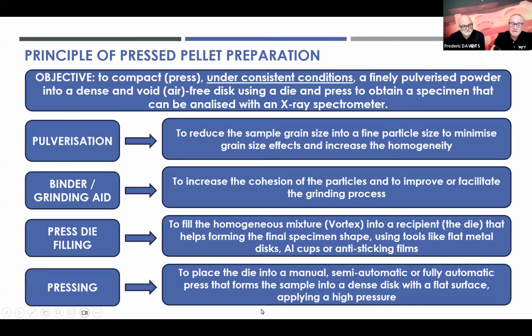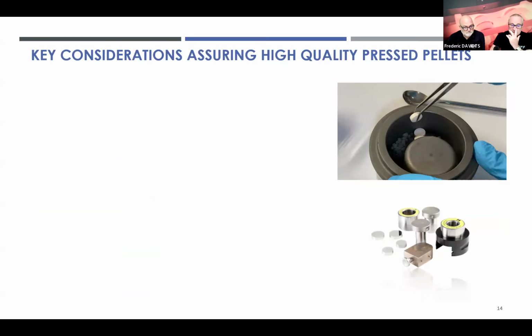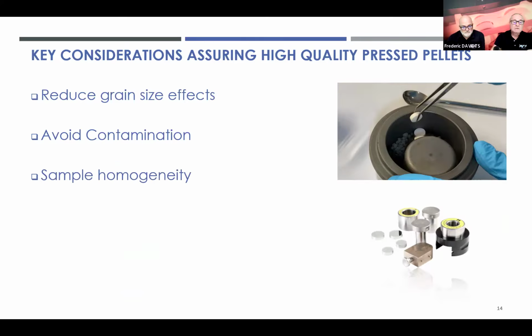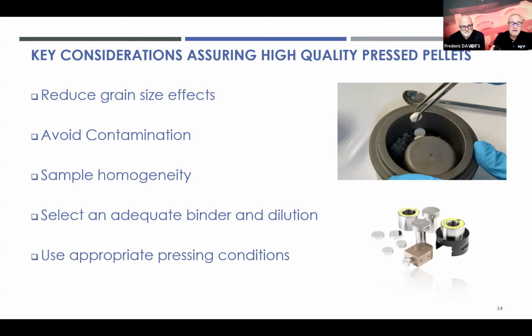And at the end, we're going to press. So we place the die into a press that can be manual, semi-automatic, or fully automatic. Frederic will talk more about all the types of presses that XRF Scientific has available. And generally, we're going to apply a high pressure, which is generally a couple of tons. Now, some key considerations to assure high quality. First of all, we need to reduce the grain size effects. And in the next pages, we will continue talking about all the details here: grain size effects, avoiding contamination, taking care that we have a nice homogeneous sample, selecting an adequate binder, and thus also dilution, and using appropriate pressing conditions for the sample size and weight that we want to create.